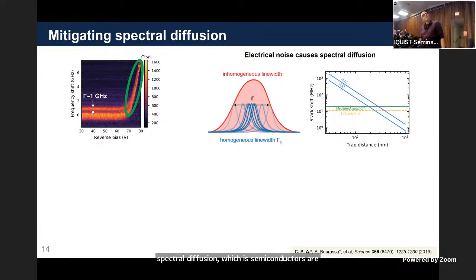There's fluctuating charges. It turns out that a single charge popping in and out of existence 200 nanometers away from our defect is enough to shift us by more than a line width. So it's extremely sensitive to nearby charges. And because semiconductors and real solid state systems are really noisy, this thing's just bouncing around all the time because there's this fluctuating bath of electrical noise.